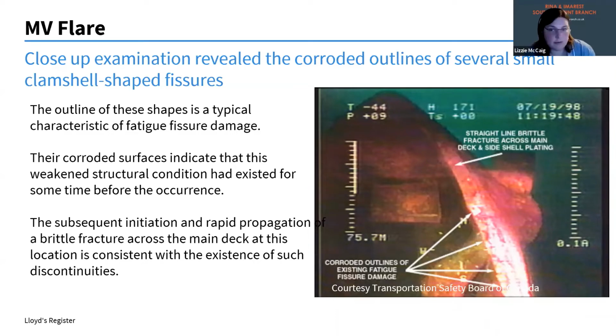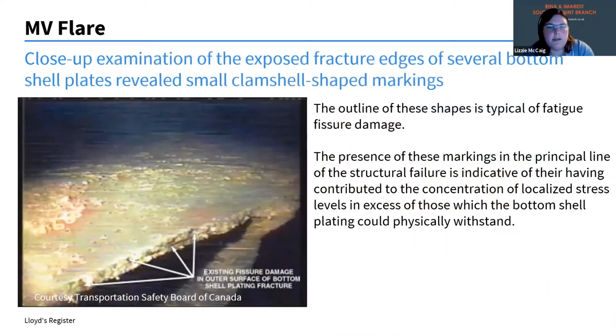Then you can see here that you've got more of these clamshell-shaped markings in this bit here, and Transport Canada found that this location in the principal line of structural failure indicated that they'd contributed to the concentration of localized stress levels in excess of those which the bottom shell plating could physically withstand. That said, she'd been sailing around for quite some time with these fissures, so why did she fail? Why did the ship break in two on this particular day?